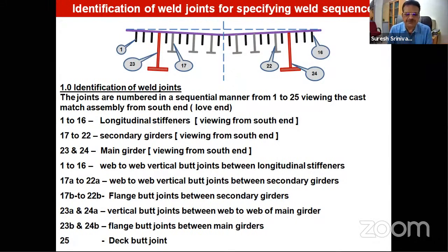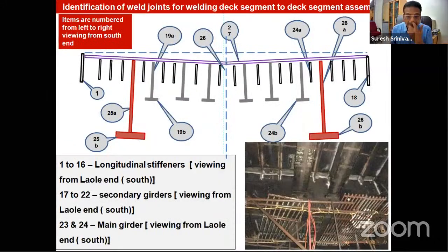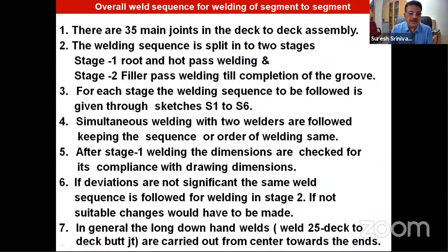So it was a step-by-step procedure, because it is next to impossible to predict the distortion of such a large complex structure. So you can see the bottom side view and how we went about welding in a very specific sequential manner. Totally there were 35 main joints in the deck-to-deck assembly, and the sequence was split into 2 stages. All are multi-pass welding.